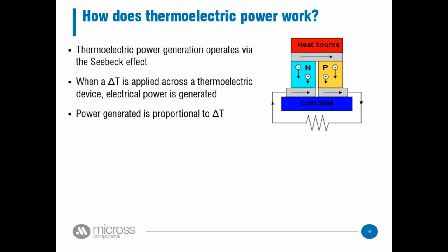So when we have this delta T generated and our charge carriers move from the hot side to the cold side from the thermoelectric effect, you essentially can create a circuit where you have charge carriers moving and you have power. The amount of power that you get is going to be dependent on the delta T. ZT is important, as I talked about, but even more important is delta T. The more temperature difference you can generate from the hot side to the cold side, the more carriers are going to be moving from the hot side to the cold side. The more carriers you have, the more current you have, the more power that you have.